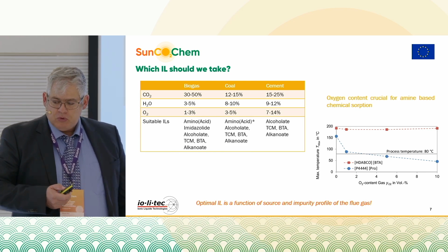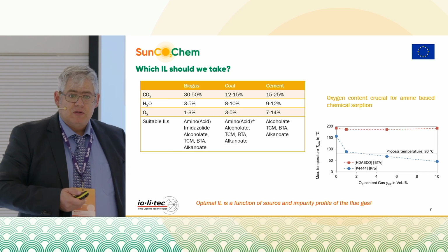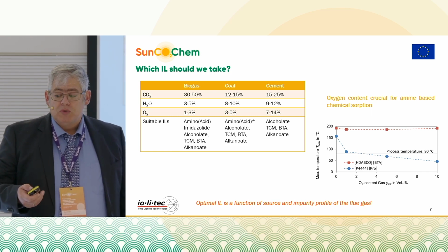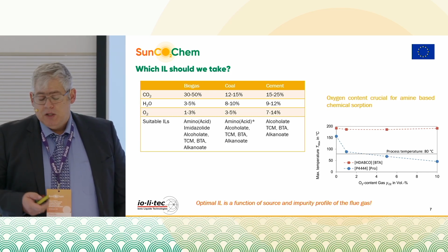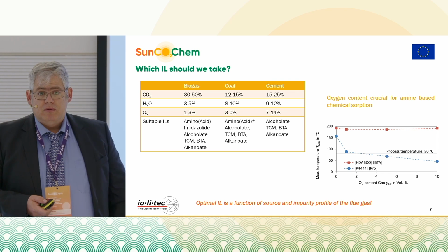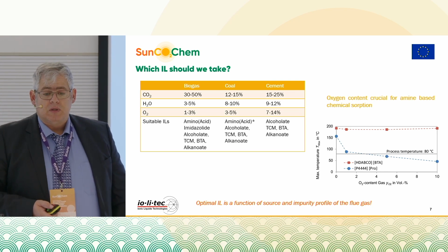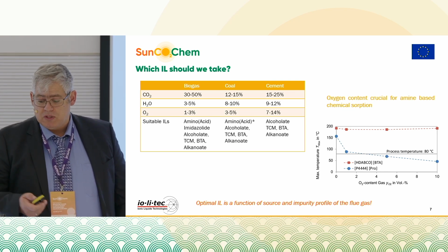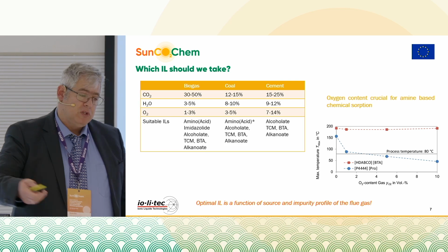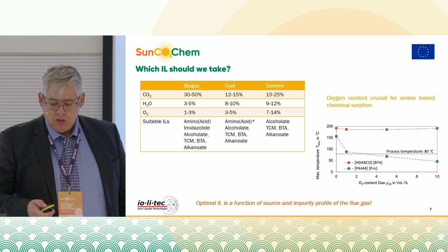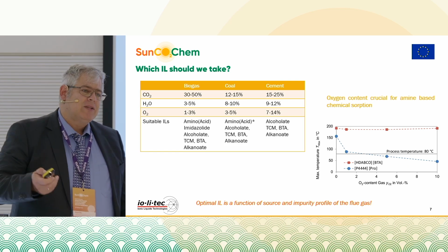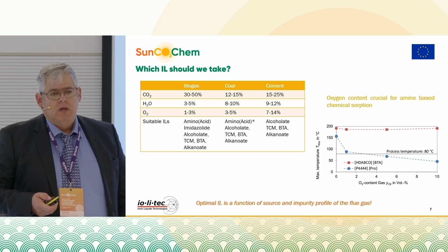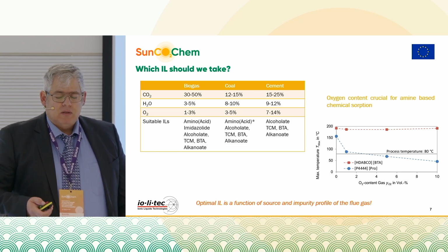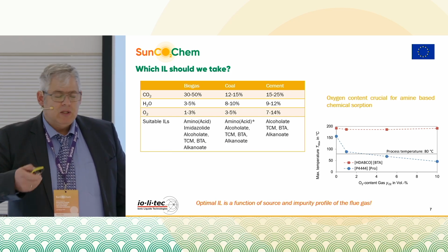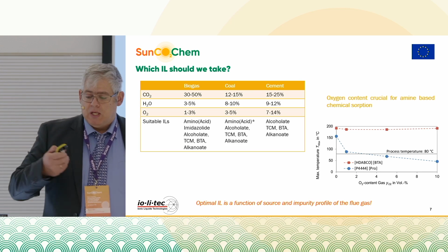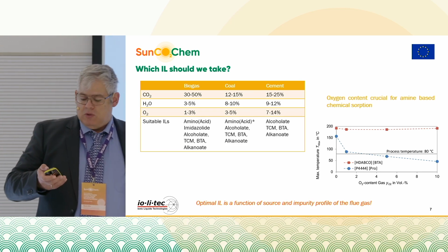What's probably important at this stage is to say that in most cases the oxygen content is probably the most unpleasant contaminant in your flue gas, because this limits you the most in the choice of ionic liquids, which doesn't mean that you cannot find a solution. It just means that the most active chemical sorbents are, as you can guess, amine based, or ionic liquid amine based, put it whatever you want, but generally, this is something you cannot use in that case.